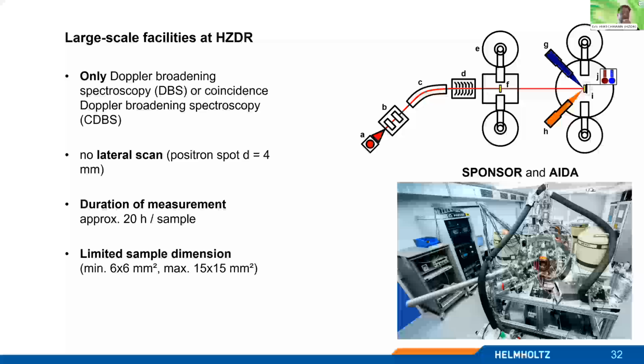As I said, you can only do Doppler measurements, which means all the information from positron lifetime can't be gathered, but all the information from the Doppler broadening which I mentioned before can. We can do no maps and no lateral scan, so the beam size is more or less the same. The measurement time here is approximately 12 to 20 hours per sample, for the full scan. Also you have a limit to the sample size. It's better to have a 10 by 10 millimeter sample, as large as possible, but it depends a little bit on how we can place the sample on our sample holder.